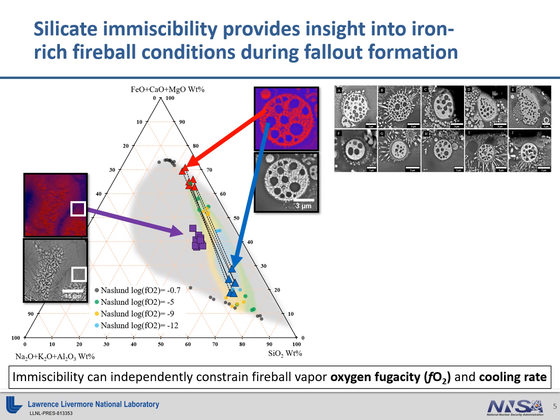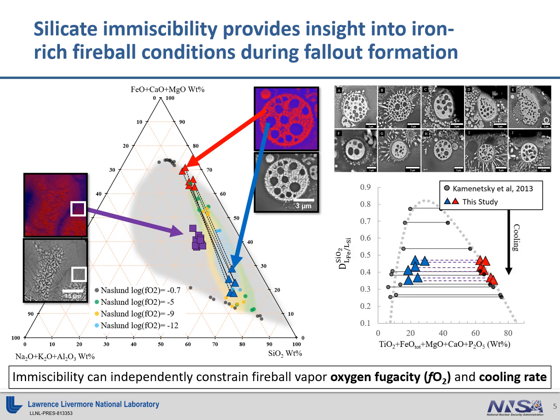In fact, it just so happens that the two liquid compositions are quite sensitive, both to the oxygen partial pressure in the system during liquid phase separation, as well as the thermal quench behavior as the phase separation occurs. This is serendipitous, as it suggests that these structures provide new avenues to independently constrain fireball formation conditions, allowing us to better understand the conditions of fallout formation in iron-rich environments.